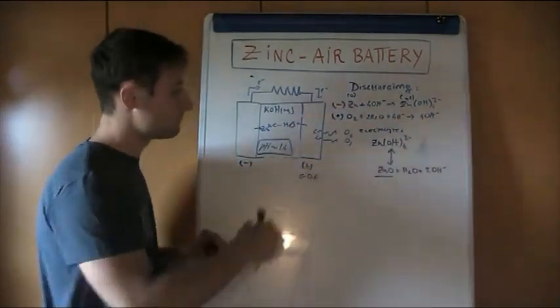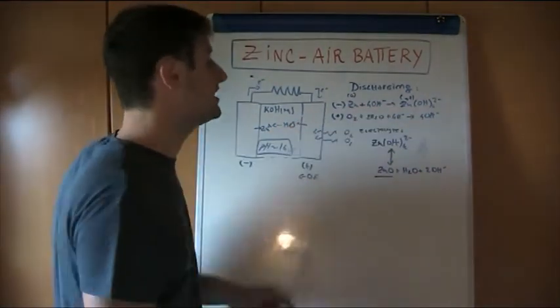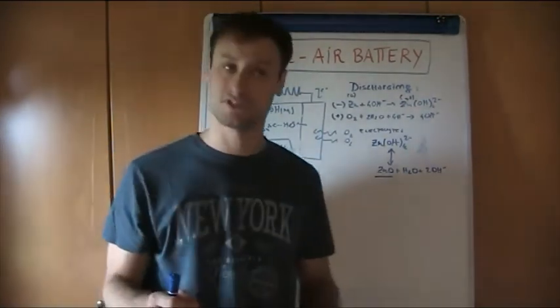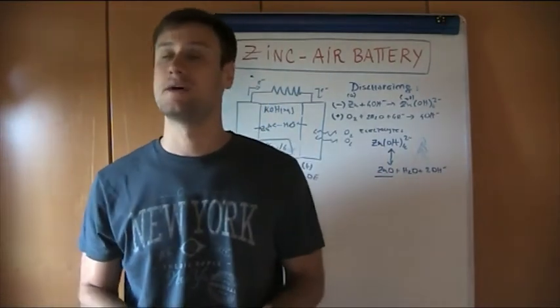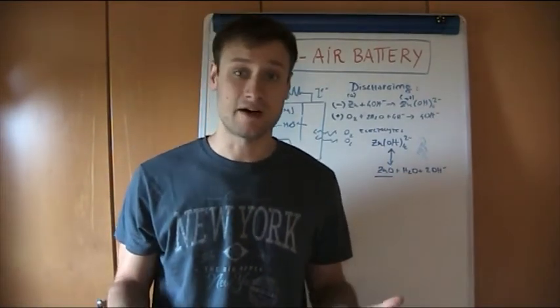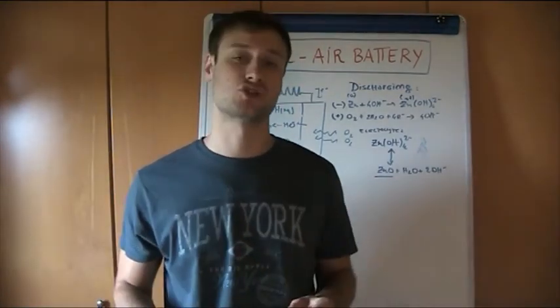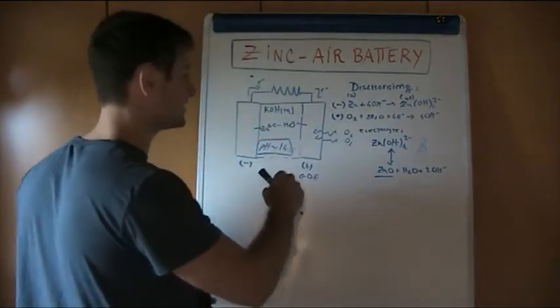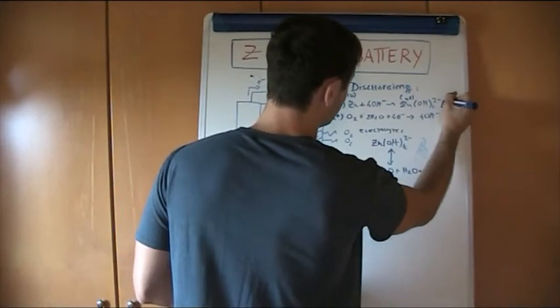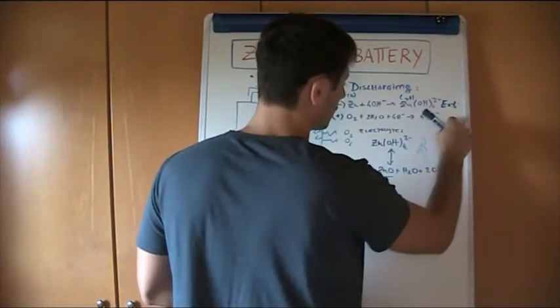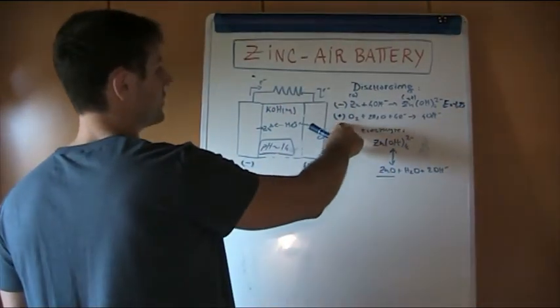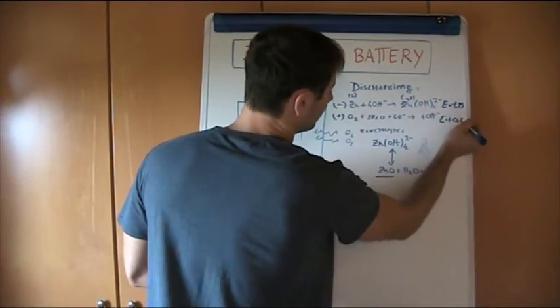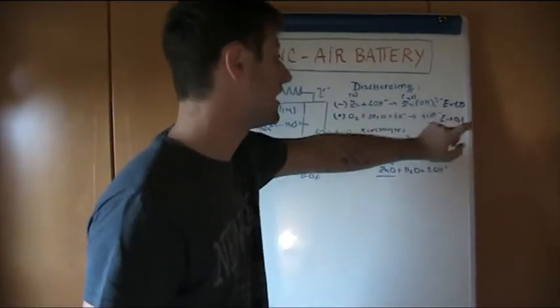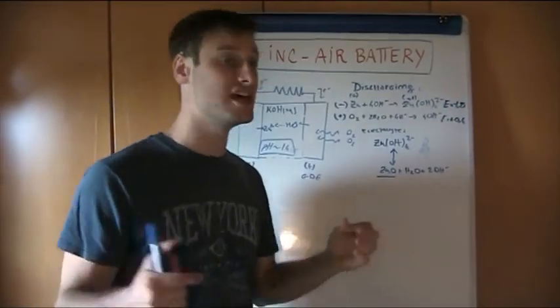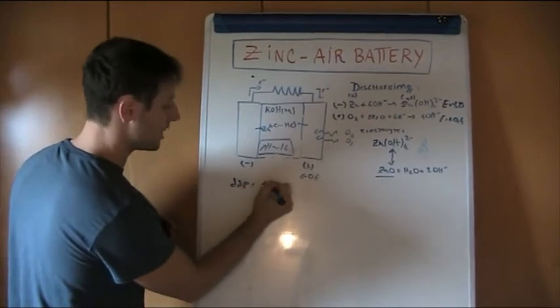And it's also extremely important to remember another aspect, the reduction potentials of this reaction in this pH condition, because we need to remember that sometimes, obviously not always, a different pH can change the reduction potential, according to the Nernst equation. So in this situation we can say that the reduction potential of the zinc is equal to minus 1.25 volts, and the one of the oxygen reaction is plus 0.4, minus 1.25 volts plus 0.4 volts. So the difference, the DDP, is equal to 1.65 volts.